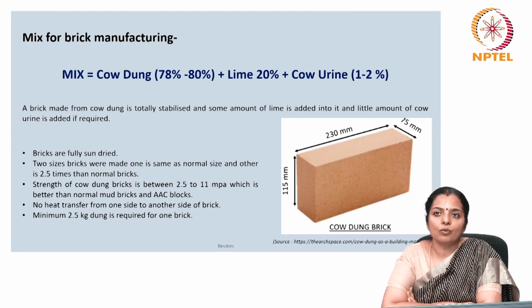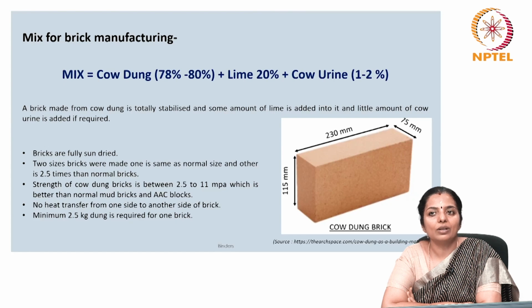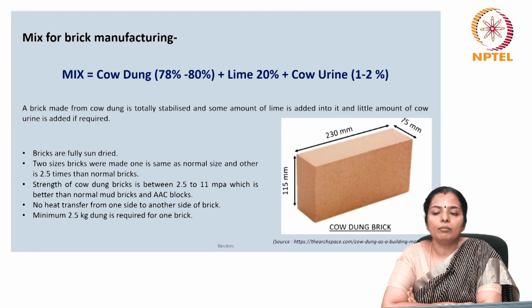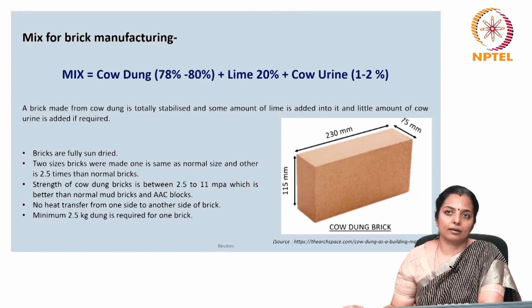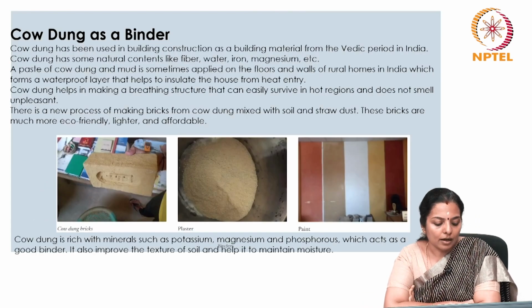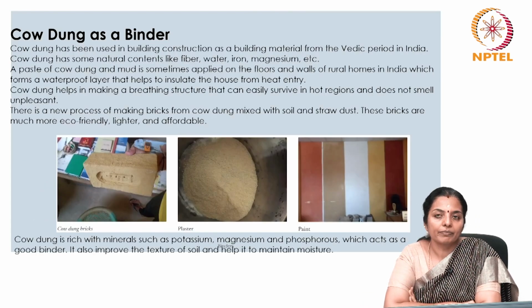The strength of cow dung brick is between 2.5 to 11 megapascals, which is better than normal mud bricks and AAC blocks. No heat transfer from one side to another side of the brick has been seen to happen, and a minimum of 2.5 kg dung is required for one brick. Let us now look at cow dung also as a binder.